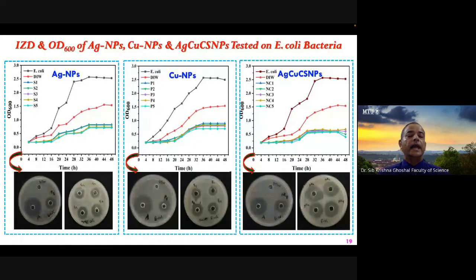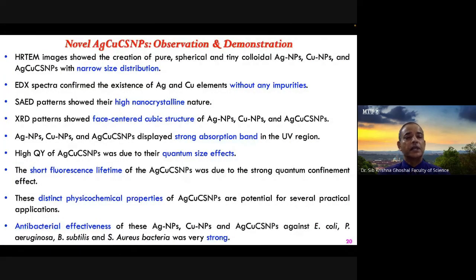And you can see here that with time and with the improvement of the size of the nanoparticle, when we reach the optimum nanoparticle, which is the S4 and S5 sample, bacterial growth is totally hindered, and the bacteria is totally wiped out from the culture. This is the proof that these core-shell nanostructures are highly efficient for antibacterial application. So these novel silver-copper core-shell nanoparticles, or any other combination of these with organic nanoparticles such as turmeric, mint leaf, curry leaf, cinnamon, clove, black pepper, cardamom, we are trying to get different combinations.